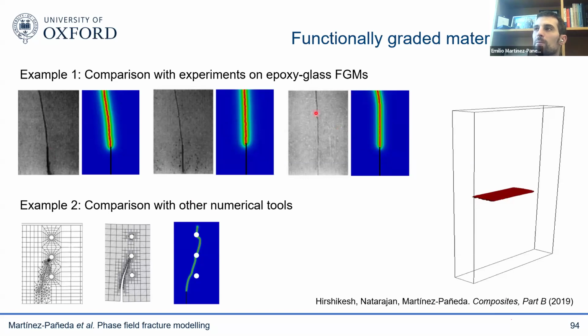You can see that the model seems to agree very nicely with experiments. We can calculate this in 2D and 3D. You can see a comparison with other techniques here. Notice that the phase field not only is able to predict nicely what happens, the crack trajectory resembles what happens in other techniques, but because the method can predict crack nucleation as well, we can see that the crack can go all the way to the defects, to the second defect.